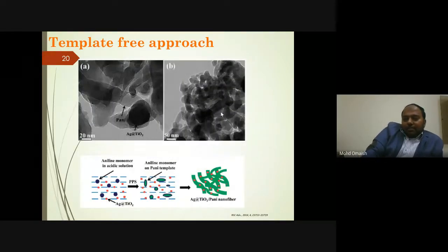This is simple polymerization, a rapid mixing technique. This is template-free; there is no template used. This is a simple acid, and we get very good elongated, short nanofibers. It is only acid, oxidant, and monomer, and that's done.